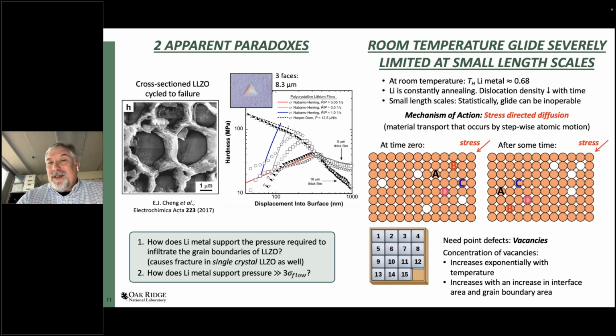Its efficiency depends significantly on three factors. I'm sorry, I should have put them on the slide here. The first one is basically how fast you're trying to move lithium out of the way, so it's related to our current density, and again, how fast you want to charge your battery. The second factor is how far you're asking the lithium to move, which is effectively related to the diffusion length. And the third factor is temperature.